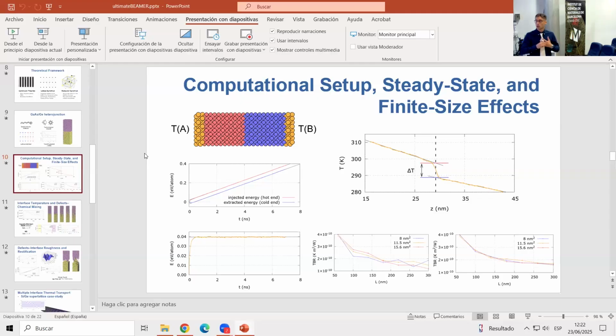Why? Okay, there are several reasons. The prominent one is that you are not describing the continuum, so the infinite size system, meaning that the number of phonon modes that you have for the left side and the right side, this is a simplified picture still, but the number of phonon modes that you have for the two materials does not mimic fully the number of phonon modes that you have for an infinite system. So you will have a more pronounced difference in the two phonon spectra, which implies less compatibility between the two.